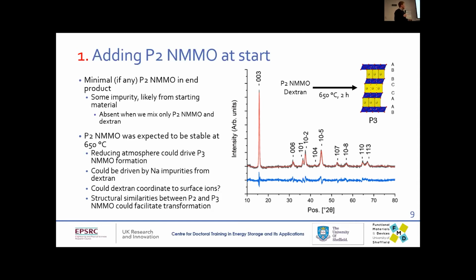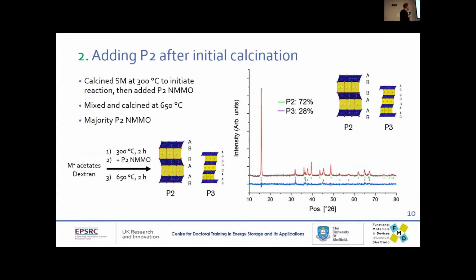And it could be that there are some structural similarities between P3 and P2 that are causing this crystal growth, which will become relevant right now. So this is the second route where we're drying it, calcining it in this pre-calcination step, and then adding the P2. So we're getting just very well mixed metal ions in a powder growing around this pre-made P2 crystal. And in this situation, where I've just got the loose powder and calcining that at 650 degrees, we get a majority P2.